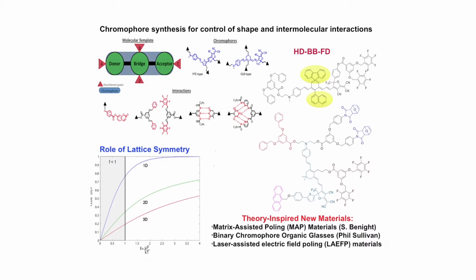Well, we've learned that we can impact properties such as electro-optic activity by modifying chromophores, for example, to change their fundamental shape. But my students and Bruce's students have also shown, and Alex Jen and his students have shown, that you can modify chromophores with groups that undergo long-range intermolecular interactions like coumarins or benzene-perfluorobenzene materials, where these dipolar and quadrupolar interactions promote long-range cooperativity that impacts the lattice symmetry that the chromophore senses. And as shown by this theoretical slide, where this is the acentric order parameter, this is the effective poling field, as you go from a three-dimensional lattice felt by the chromophore to a two-dimensional lattice, you double the electro-optic activity, or the acentric order parameter in the electro-optic activity.